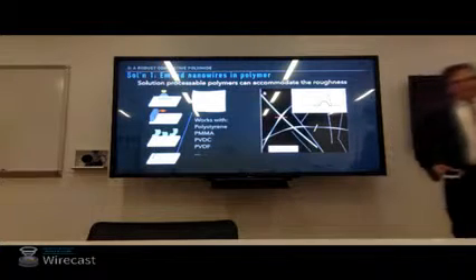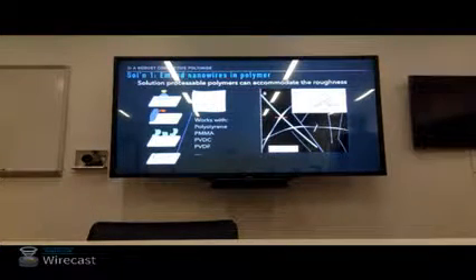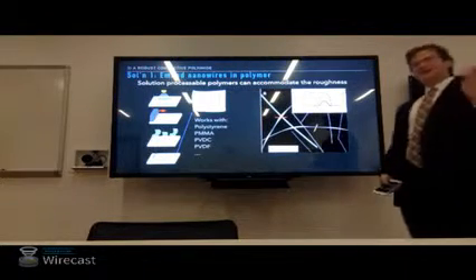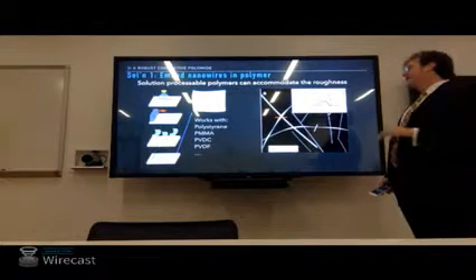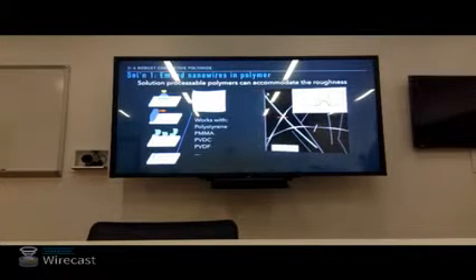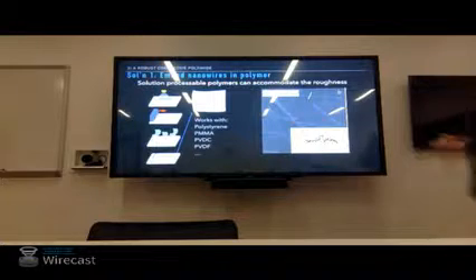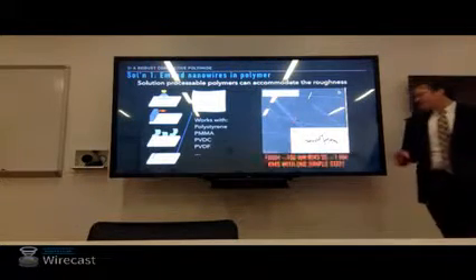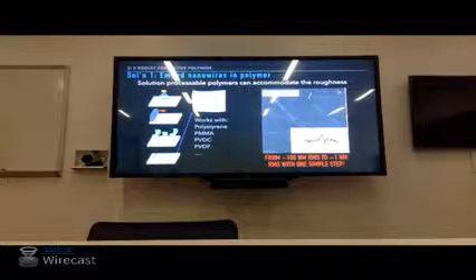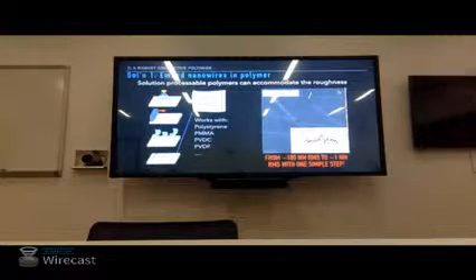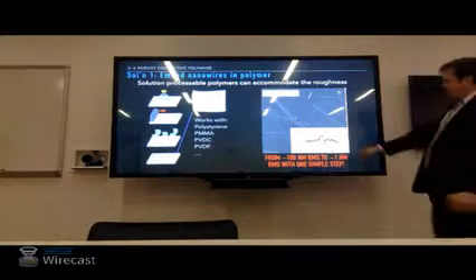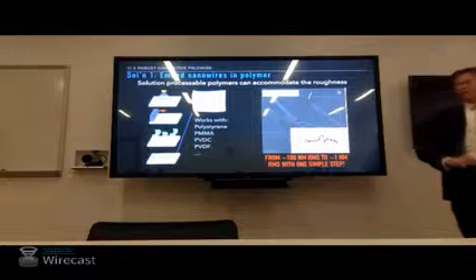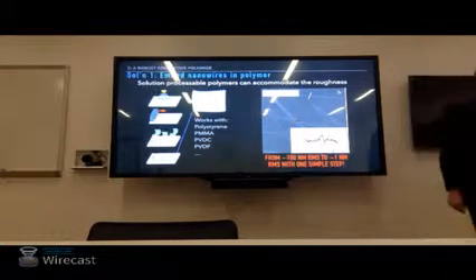Then we dry the polymer, which was in solution phase. Now it's a solid. We hope and pray that this polymer detaches from the glass, and we hope and pray that the buried interface there has the nanowires held against a flat interface now. It'll be conductive. So this solution takes our AFM that was showing hundreds of nanometers RMS, and in this one simple step, we go from hundreds of nanometers RMS to possibly single nanometer. So this is what the nanowires look like embedded in a polymer. We see maybe a 2 nanometer bump now around a nanowire, and junctions now go into our surface instead of out.